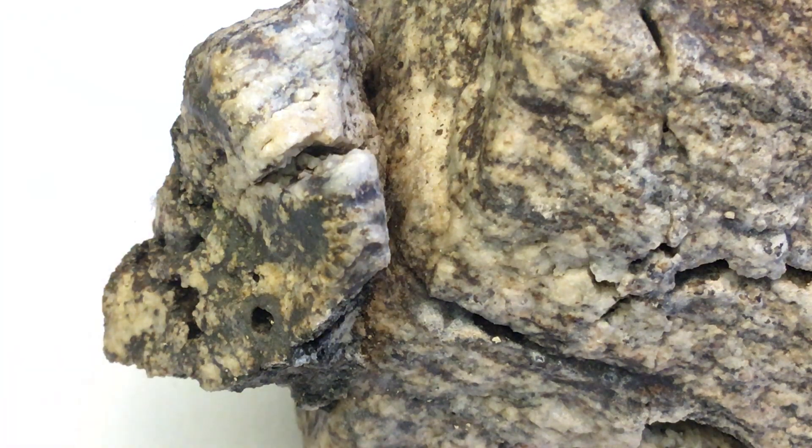This is a good indication that very high temperatures were achieved, likely with a considerable volatile pressure in the system. And this is a very early form of artificial melting of rocks in order to increase the value of, in this case, the fortification.